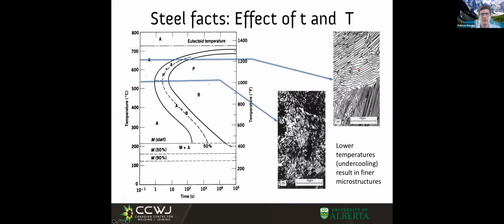In this case, because it was a eutectoid steel, it transforms into coarse pearlite. Because it's hot, diffusion can move fast, and because diffusion moves fast, it can cover longer distances. The real science is way deeper than I'm making it sound, but it's along these lines. If you're hotter, you can cover longer spaces because diffusion moves faster, and you end up with coarser microstructures. If now my holding temperature was at 540 degrees, I would have a different start temperature and a different finish temperature.